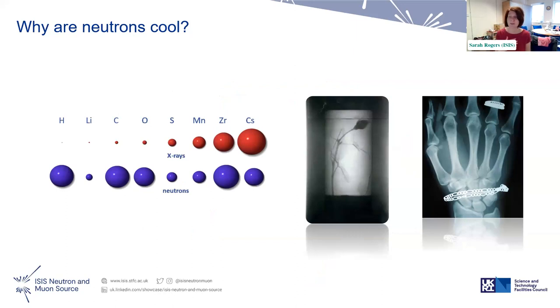For neutrons, the interaction with the cross-section is totally different. It's totally random, in fact. And you'll see from the blue blobs there that the interaction with light elements is actually quite strong, so hydrogen, carbon. And the classical image there you'll see of a neutron image is that of a rose in a lead casket. And in fact, the lead is pretty much transparent to the neutrons. They whistle straight through. But the rose, which contains carbon, hydrogen, water, interacts with the neutrons very strongly. So hopefully you can see that they're actually very complementary techniques. If you use both together, you get a very clear, very detailed picture of what's going on in your samples.